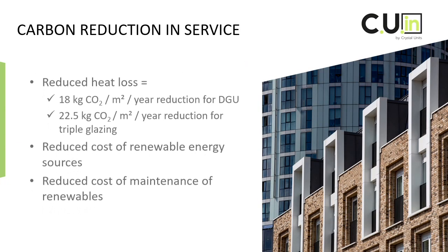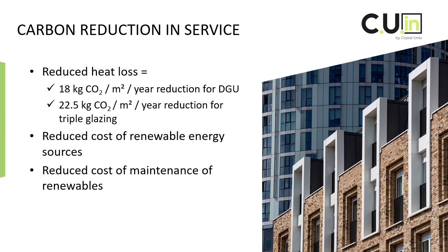Suspended film glazing outperforms standard DGU in carbon emission in service. Standard double glazing results in 1.0 watts per meter squared Kelvin heat loss, whereas double glazing with suspended film technology results in 0.4 watts per meter squared Kelvin heat loss, which is 0.6 watts per meter squared Kelvin better. This reduction in heat loss means that 18 kilograms of CO2 is reduced per meter squared of glazing per year due to the lower energy demand on the heating system.